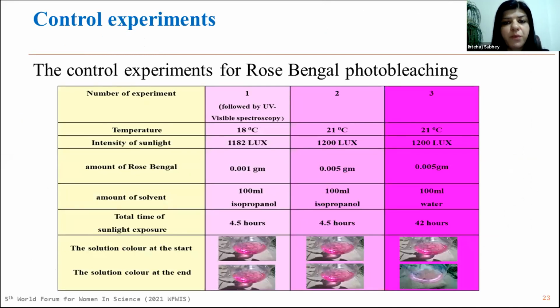The control experiments for rose bengal photobleaching. The purpose of the control experiments: firstly, we just used rose bengal in isopropanol without benzophenone. The purpose is to know the effect of benzophenone in the photobleaching or change of color of the reaction. Here in the first experiment, we used 0.001 gram of rose bengal in isopropanol. We see no change in color after exposure to sunlight. When we increase the amount of rose bengal to 0.005 gram in isopropanol, also we don't see change in the color.